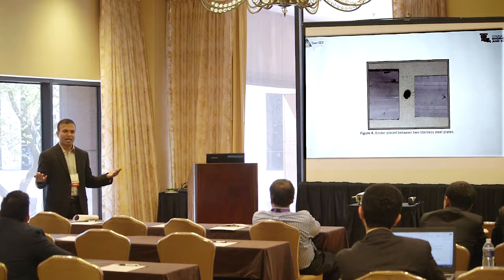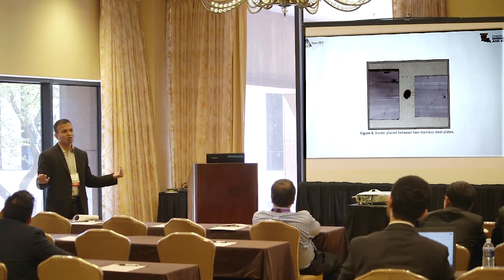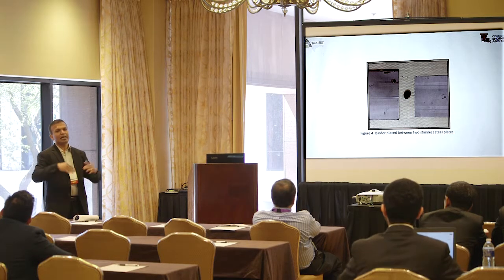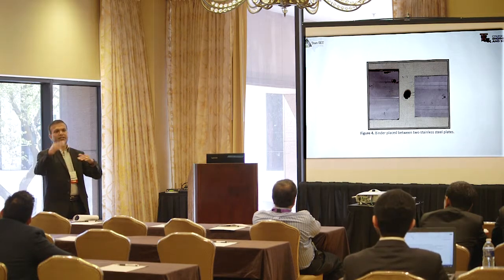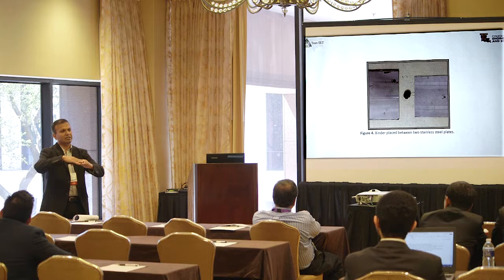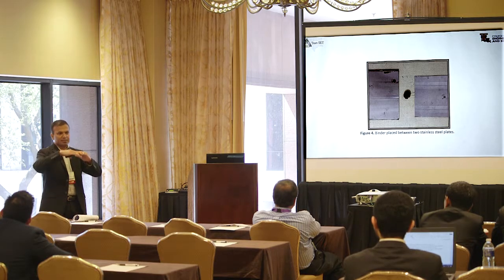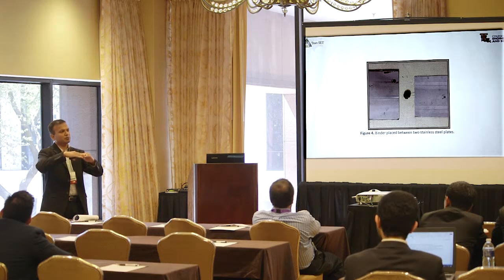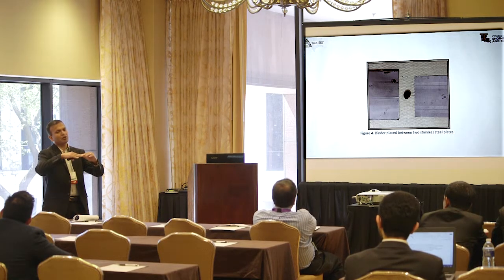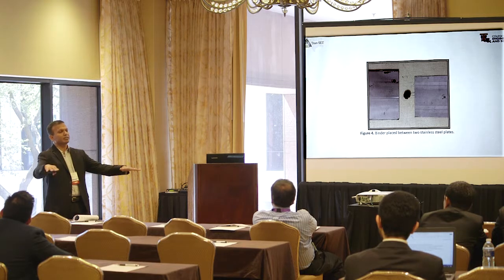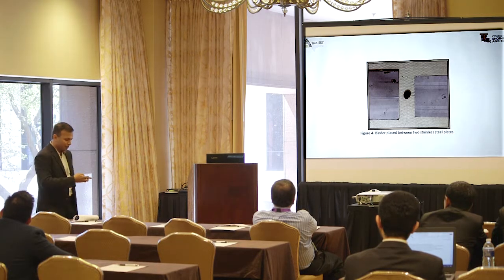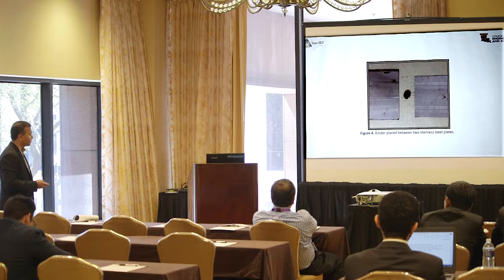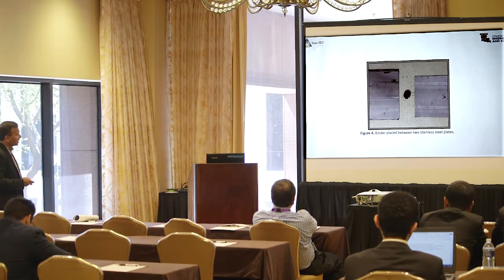weak in axial force, and also it takes a long time because of the delayed recovery of the binder. So say that you compress the binder using a DSR and precisely get your thickness for the sample preparation method, but later on you have to wait for hours to get all the delayed recovery gone. There is a delayed force there.